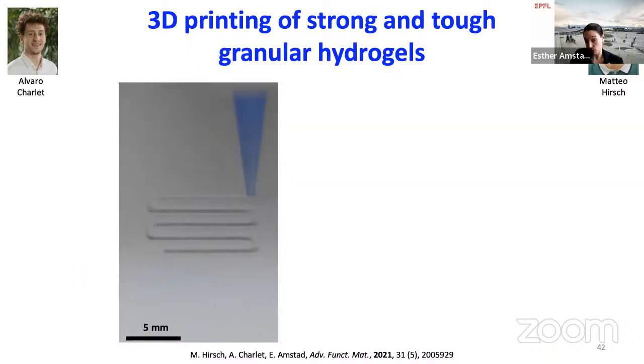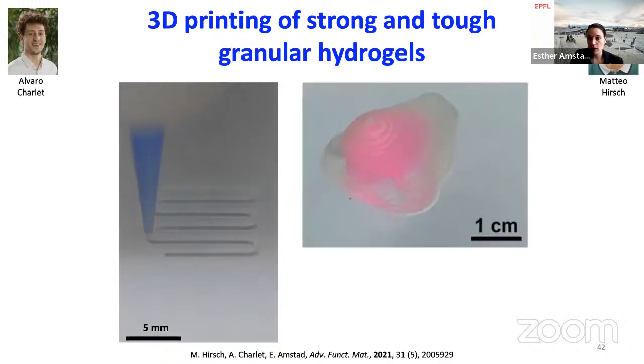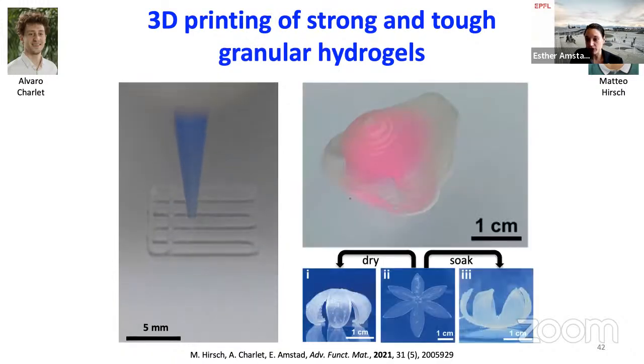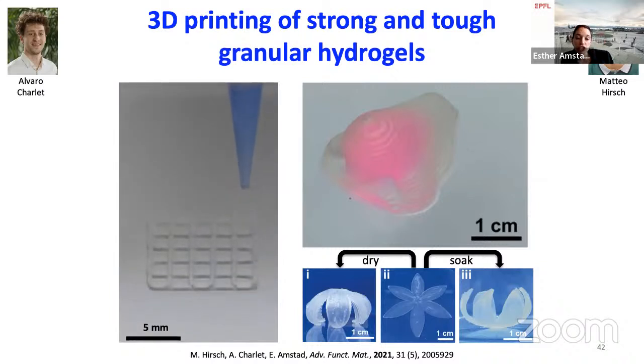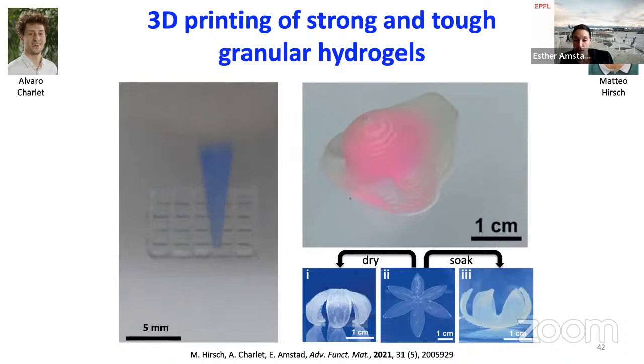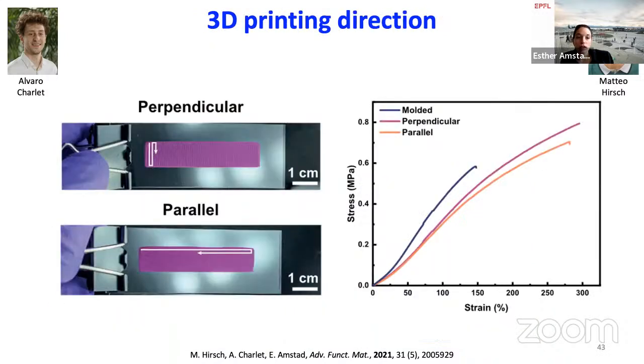Just quickly to show you how you can 3D print this, you can do macroscopic centimeter-sized structures, and because the 3D printing allows you to locally change composition, you get shape. We can design shape morphing materials. Because of this percolating network that is isotropic, the mechanical properties are isotropic as well. So we do not see an influence of the printing direction on the mechanical properties of our 3D printed materials, which is something that is quite unique for 3D printed polymeric materials.